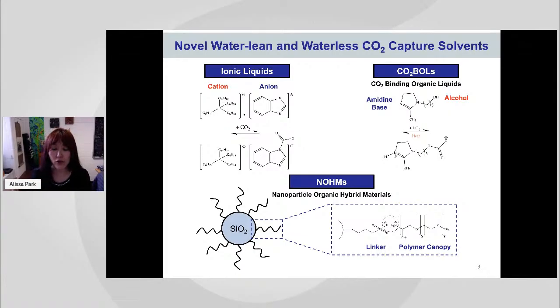So I'm not going to go into too much detail on ionic liquids or CO2BOLs. There is a lot of very exciting research going on in these areas. But the part I really liked about ionic liquid is that this material has almost near zero vapor pressure. And that's a really interesting property for liquid solvents, because when you try to do temperature swing between 40 degrees C to 120 degrees C, having zero vapor pressure is really fantastic for minimizing any fume produced, as well as for thermal stability.